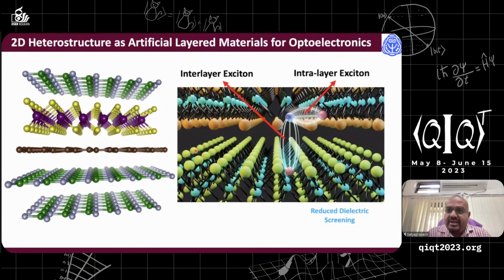One particular aspect of these layered materials which is interesting is the optical property. Here I have shown the interlayer exciton and intralayer exciton. When you do heterostructuring, particularly vertical heterostructuring, the interlayer exciton, which is otherwise not present, starts appearing in this material, and it has great application in optoelectronics and lasing.